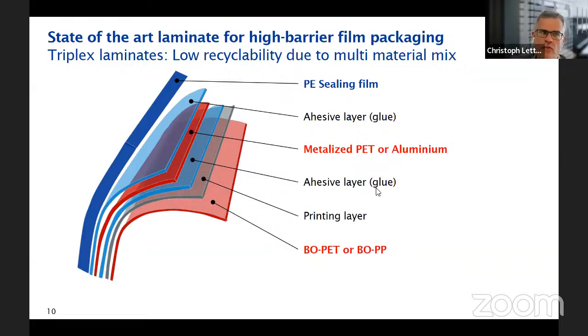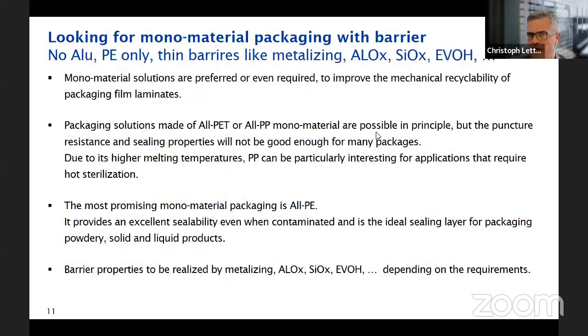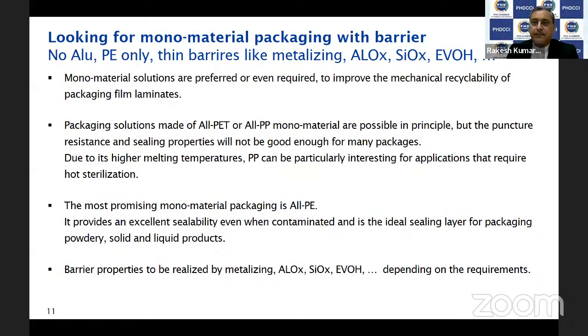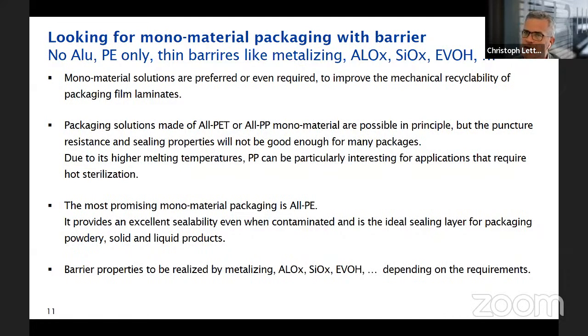This is showing the triplex laminate. Still true what I said so far: a nightmare for recycling, so we have to find a solution for that. We are looking for a mono material solution where no aluminum is involved, only PE, and a thin barrier function realized by technologies like metallizing or AlOx or SiOx, or maybe even a very thin EVOH layer giving some barrier properties, because that's the difference between the duplex and the triplex laminate. The triplex laminate gives me a barrier function. And this is for sure the challenge if we look at the solutions which have to be found here.